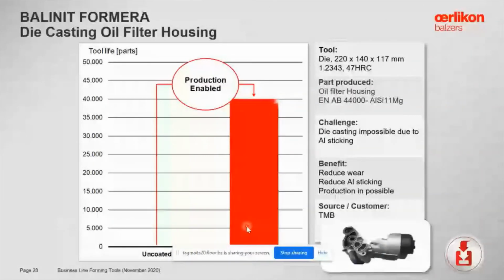Here we also provide BALINIT Formera for die casting, and this is under testing now for die casting of oil filter housing. We could see significant improvement, and this enabled the production. Earlier die casting was impossible due to aluminum sticking, but after BALINIT Formera coating, we could at least produce 40,000 components. This was an oil filter housing, aluminum silicon with 11% silicon and magnesium.